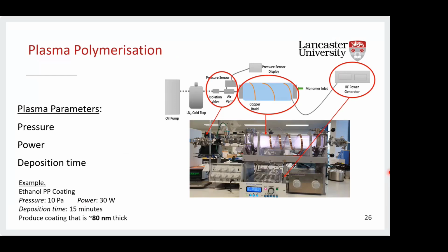Just to summarize that process using this image here, this is the existing reactor that we have at Lancaster, and the process works with this reactor glass barrel, which you maintain at approximately 0.5 Pascal. The chamber is then filled with monomer by opening this monomer inlet valve here. So then monomer moves into your chamber, increasing the pressure. So pressure is the first plasma parameter that we have to control the surface.